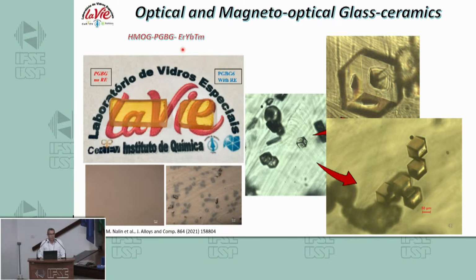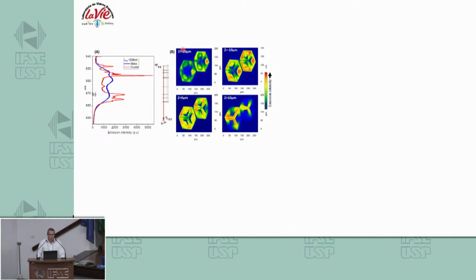What is this crystal? What is the composition of this crystal? And then we started to study this. So we could see that this is a 3D mapping of the crystal using Raman spectroscopy, but in this case we use microluminescence. We can also have this information using Raman, if the laser that we are using to measure the Raman spectroscopy is the same laser that will excite the elements inside. So you're going to see the emission, which is orders of magnitude more efficient than the Raman one. So this is why you can see luminescence. And with the size of 1 micron, that is the spot of the Raman, we can do a 3D mapping.